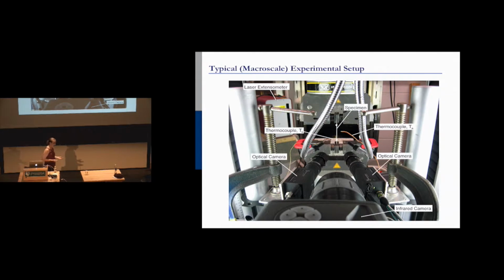So we started out this work on the macro scale. We were looking at this material in the context of stents, and we had this setup. We have 2 cameras because we're doing 3D DIC, and we have an infrared camera because this is actually a first-order phase transformation where latent heat and the extended transformation will strain interconnect. And we have a specimen, we have a laser extensometer just for a sanity check, and we have a specimen thermocouple also for a sanity check.